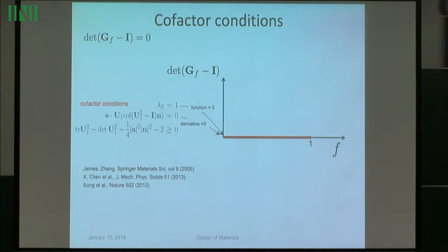So you can reduce this to algebra. It's to make the endpoints as roots. It's the old middle eigenvalue condition. And it's a quadratic function, so you make the derivative at the end 0, that's this condition. And this is the inequality that makes sure that the middle eigenvalue is the one that's vanishing.